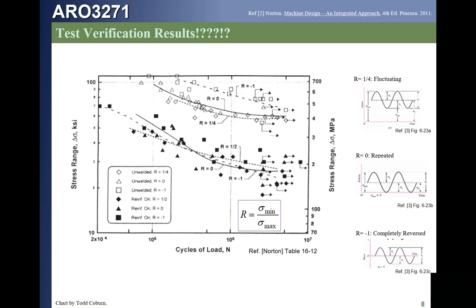When the stress ratio is 1/4 or 0, we have both mean stress and alternating stress. When R equals minus 1, we only have alternating stress with zero mean stress. Looking at the hollow squares for unwelded parts at around 10^6 cycles, parts with no mean stress have a higher allowable stress than those with mean stress. However, when we look at the solid symbols for welded parts, there is no clear trend — the scatter makes it impossible to distinguish between welds with mean stress and those without.